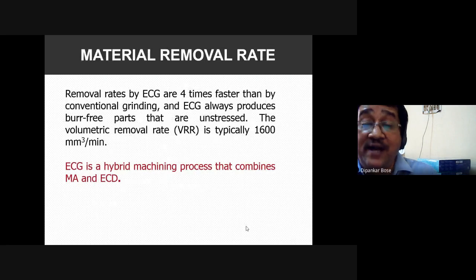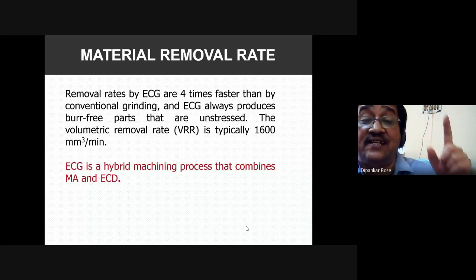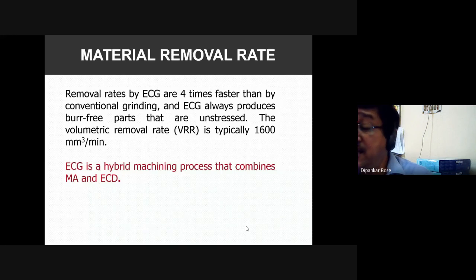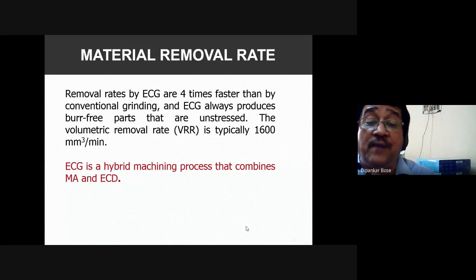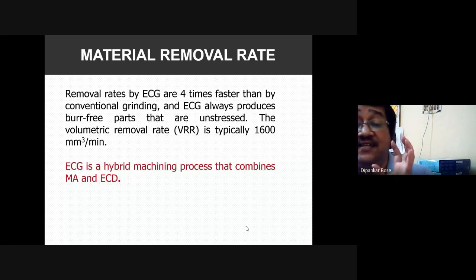Now, one important thing is that the removal rate by ECG is 4 times faster than any conventional grinding. It always produces burr-free parts that are unstressed, and the volumetric removal rate is typically 1600 cubic millimeters per minute. So ECG is a hybrid machining process that combines mechanical abrasion and electrochemical action. So this is the beginning.